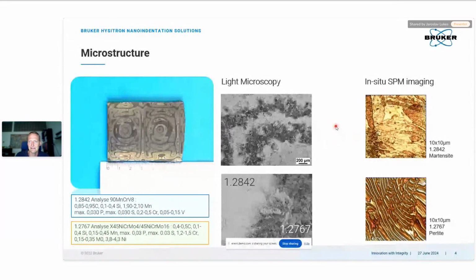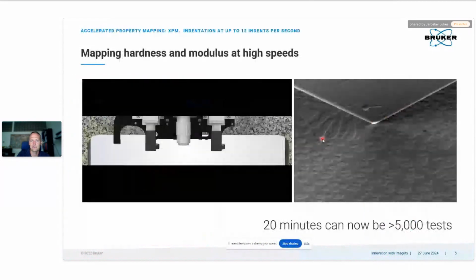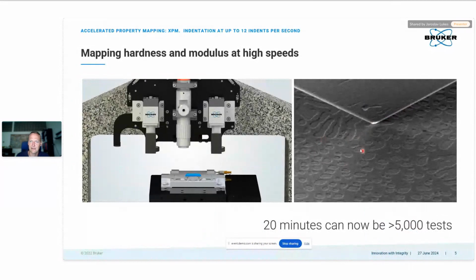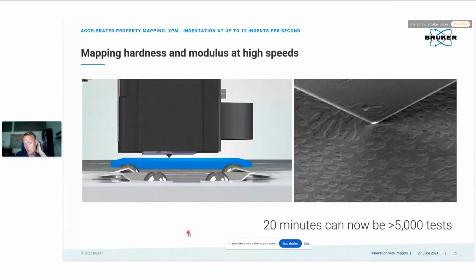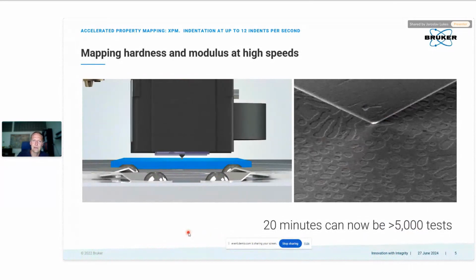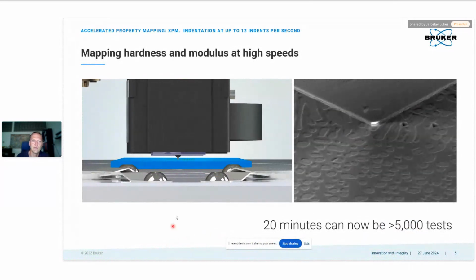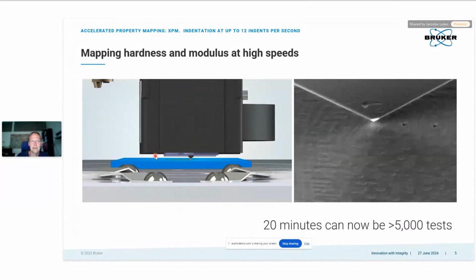So the very latest Triboindenter TI990 from Bruker enables 12 indents per second. You are running the indents in a line, so you might be able to get the contrast of the mechanical properties with respect to the different phases. How that works: you are focusing on a surface with a microscope, and then you synchronize the motion of a piezo scanner over the sample surface with the sensor that produces the indents and collects the indentation curves.